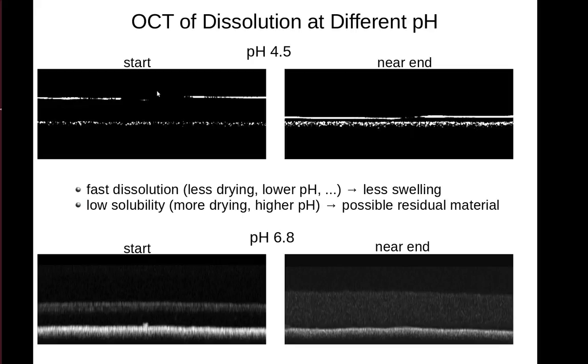An example use of the OCT for the current project of the reverse enteric films is shown here. On the top is a film cast on a microscope slide, and it's going to be dissolved at a pH of 4.5. The image on the left is at the beginning, the first cast film, and on the right it's near the end, not the exact end where the film would be gone, but near the end. On the bottom is a film of the same polymer cast on a microscope slide but dissolved at a pH of 6.8. On the left is again the start, and on the right it's near the end.